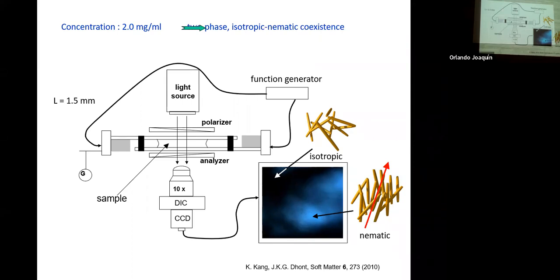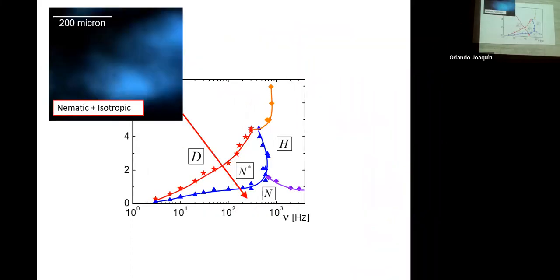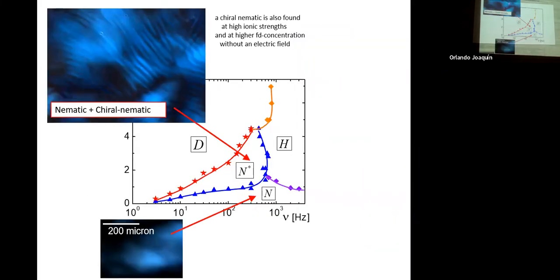So if you look at this picture again: here, the direction of orientation in the black region, the nematic director, the direction of preferred alignment, is sticking out of the plane. And here it lies inside the plane. So this is due to this turn of the nematic preferred direction.